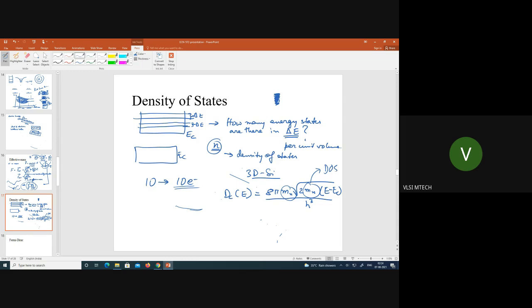Actually, since the effective mass is this approximation we do to make our calculation easier, we use different effective masses for different calculations. We have a conduction effective mass, which is used for calculating the electron movement and transport. And then we have a density of states effective mass, which is used for calculating density of states for all the electrostatic stuff. Similarly, for the valence band, it would be something similar, but the effective mass will be replaced by the effective mass for holes.